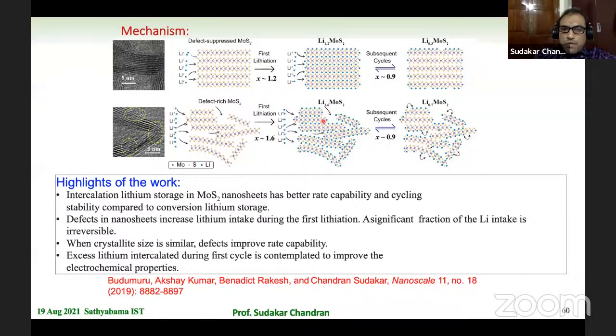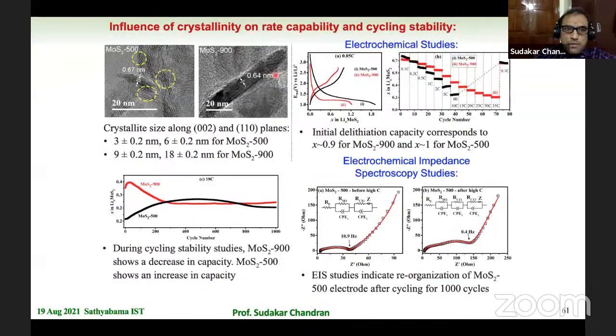So in the presence of defects, lithium diffusion becomes much easier, whereas that is not the case in defect suppressed molybdenum disulfide, and therefore the electrochemical properties get enhanced. We did analyze the extreme compounds, where a large concentration of defects is there in 500 degree annealed samples and 900 degree annealed samples, and you can see the drastic difference.